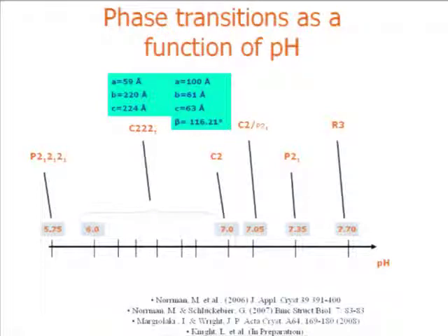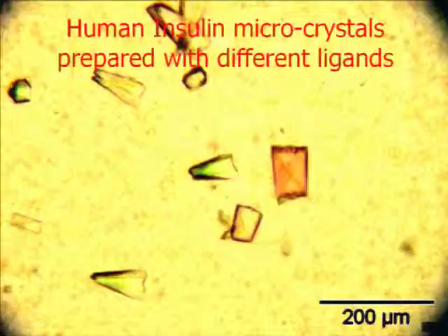So again, we try to construct a phase diagram by varying the physical chemical environment of the protein. And when we use a specific ligand and we vary the pH, look what is happening here. From 5.7 to 7.7, we got 6 different polymorphs corresponding to orthorhombic or monoclinic phases, plus 2 new polymorphs, which were then solved from microcrystal diffraction at the Swiss light source. The surprise was big for Novo Nordisk because this protein is one of the most well studied. Its function is known for 80 years, but still there are polymorphs which have not been characterized. And this is what I like in biology. You never run out of interesting problems to solve.